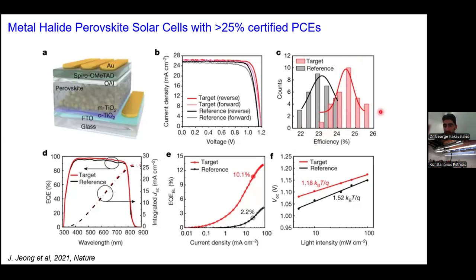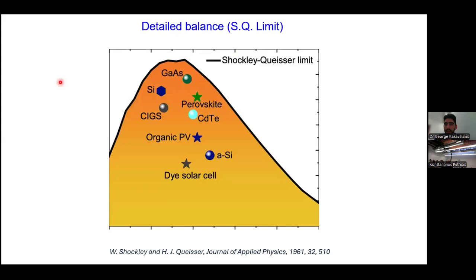26.7, as far as I remember, is the recent world record. So practically it has the same efficiency as silicon solar panels, even though this material is approximately 500 nanometers thick instead of 3 to 300 micrometers that we need for silicon. You understand the material utilization efficiency that we have here.